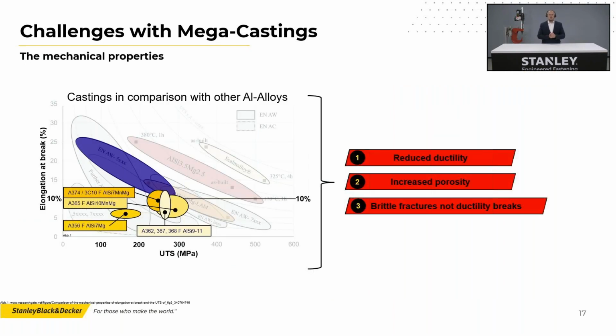And yes, there are. For example, this is now more affecting us as a joining systems supplier: the mechanical properties of these castings. On the left, you can see a graph, which is elongation at break to tensile strength. And the blue one is a 5000 aluminum alloy that most of you know. And the yellow ones are the current casting alloys that we see on the market and that are used for these mega castings. So you have AlSi7, AlSi10, and a lot of mixtures in between.